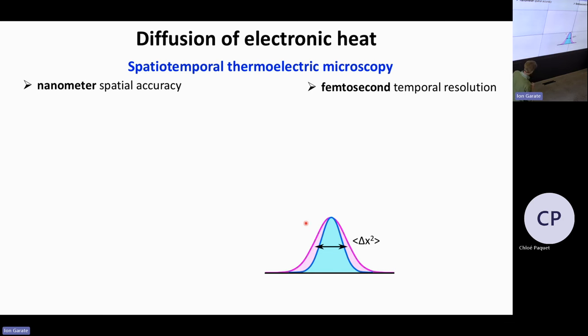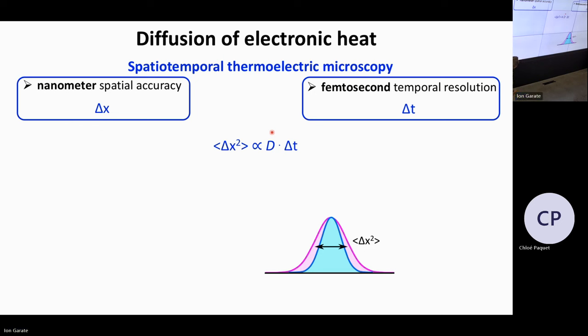So in this technique we're going to have nanometer spatial accuracy and femtosecond temporal resolution. So we have very high accuracy with which we can look at the diffusion of electronic heat in the system. As I said, this width squared scales with the delay in time and this diffusivity. That's the parameter that we're going to be extracting here.